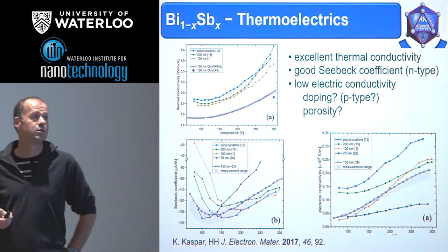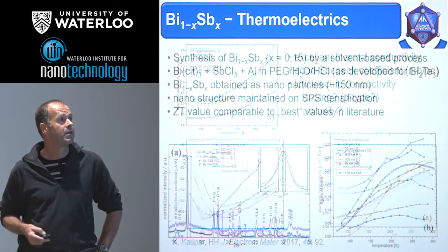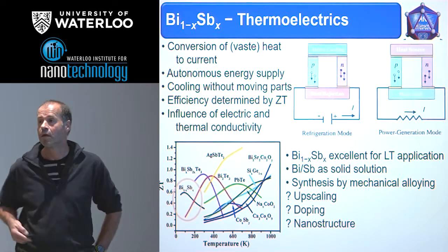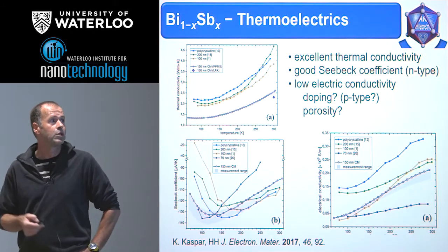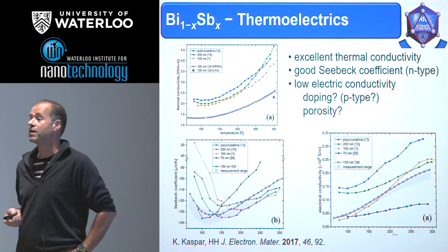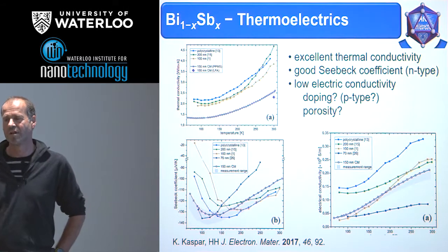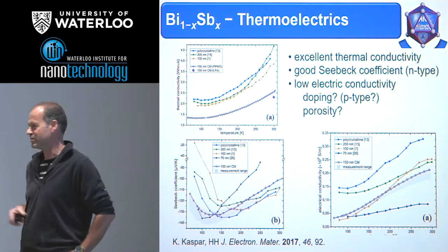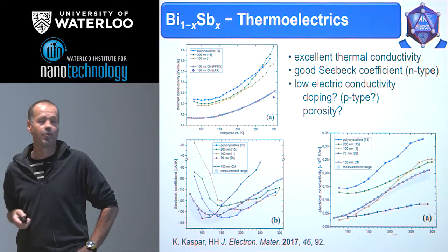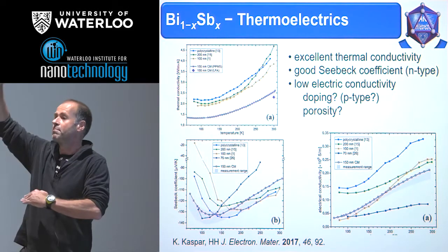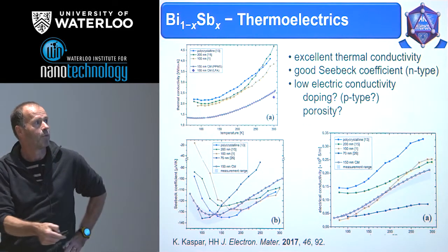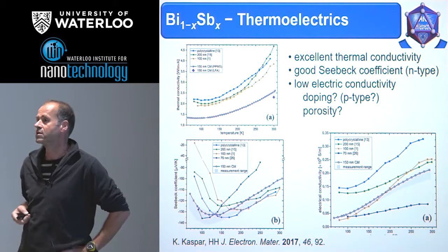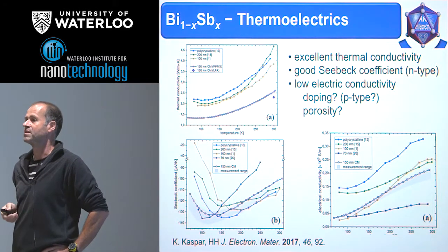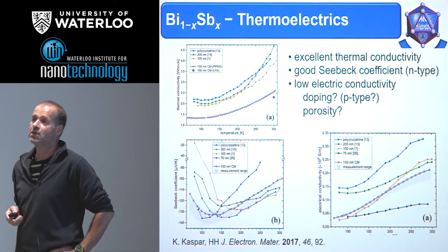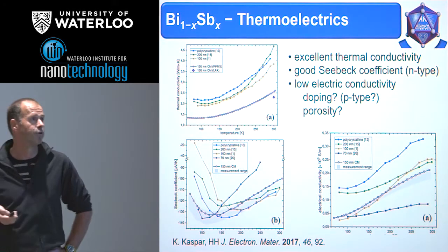And the problem is how to do the doping for the P-type, because for the application we need both. And now we are on a good way to do the doping with tin by a solution process. During the last 2 weeks, we had some important progress, so I will not talk about that. But another point is, when you do the compaction, you always have a problem with the porosity, but here we also are up to about 94% density, which is quite good to get reliable properties for the thermoelectric material.